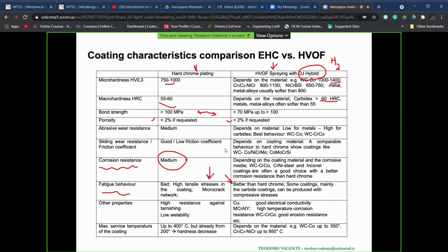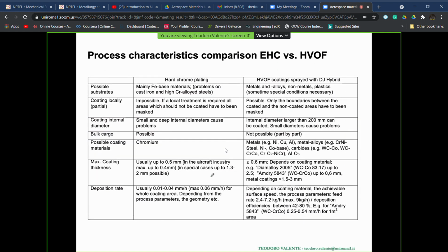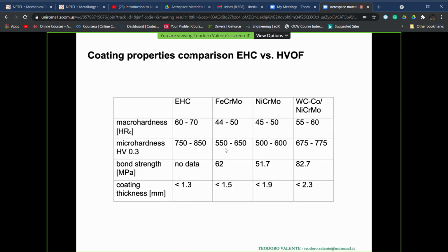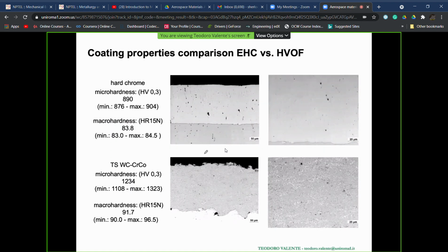You see here another table of comparisons of properties obtained by chromium plating and cermet, in which we have tungsten carbide, cobalt, but also another metallic phase, which is nickel chromium. If you see here, by comparing, we can achieve the properties and sometimes have also higher values, as we said before, than the chromium plating.